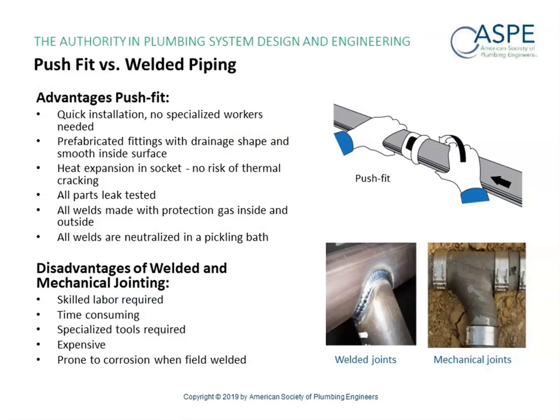The biggest difference between a push fit versus a welded piping has to do with how it's welded. If you're doing factory welds, you use an inert gas inside and outside when you make that weld. And then you want to passivate that weld in a pickling bath. So the disadvantages of welded and mechanical joining is it does require skilled labor.